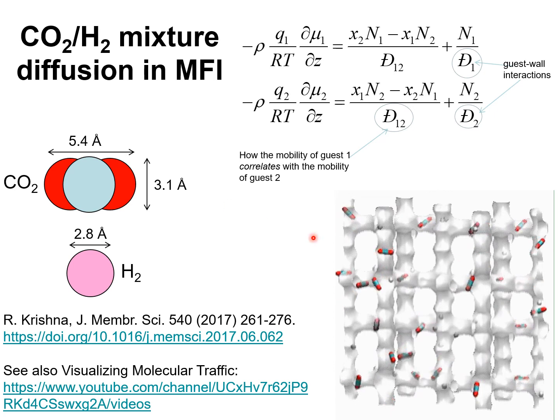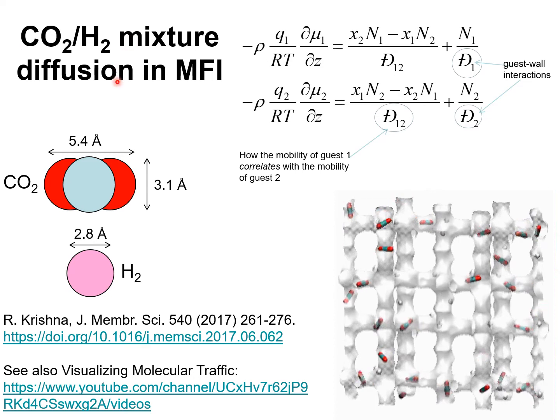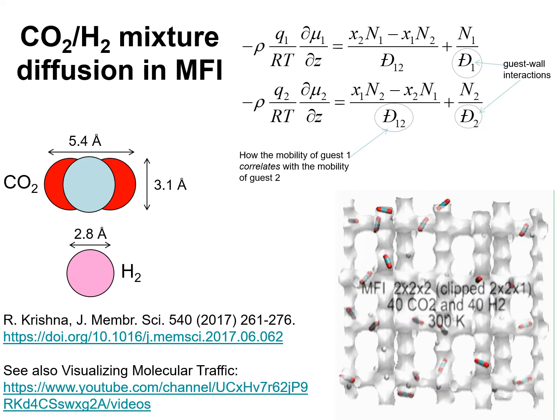In order to demonstrate this, let us consider CO2 hydrogen diffusion inside MFI zeolite that consists of intersecting channels that have dimensions of 5.4 angstrom. CO2 is a pencil-like molecule that has a much stronger adsorption strength than hydrogen, which has a much smaller size. Let's look at animations created from MD simulations.